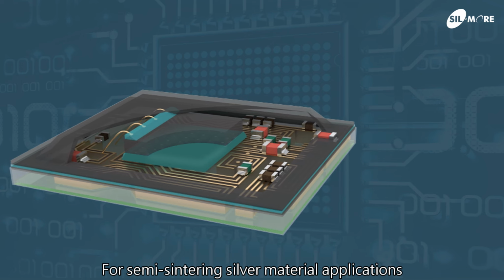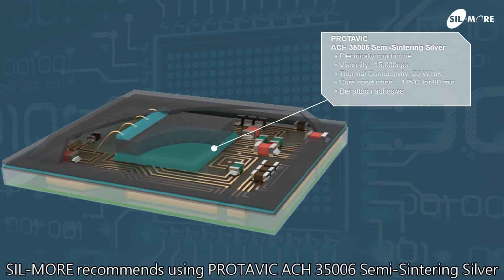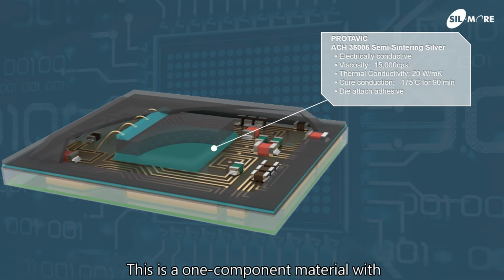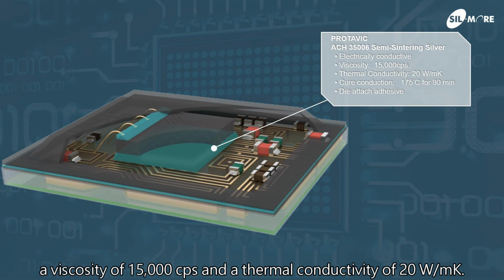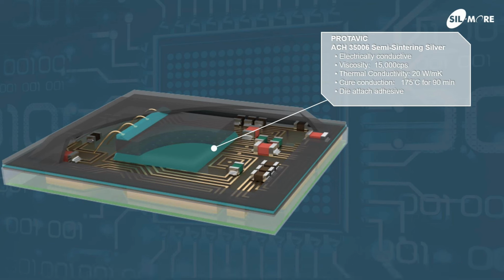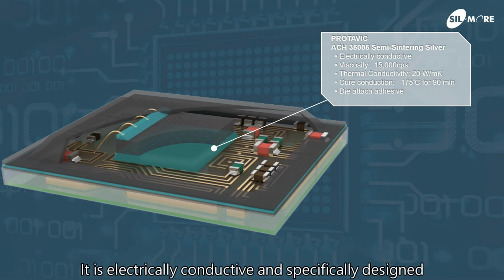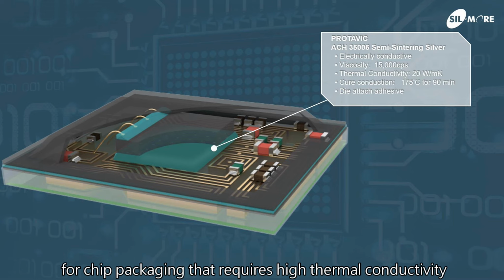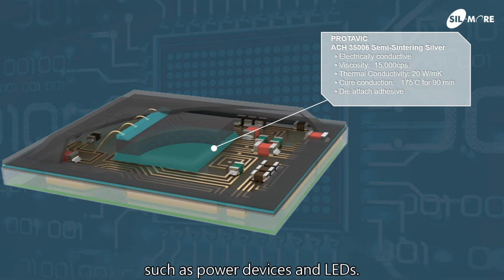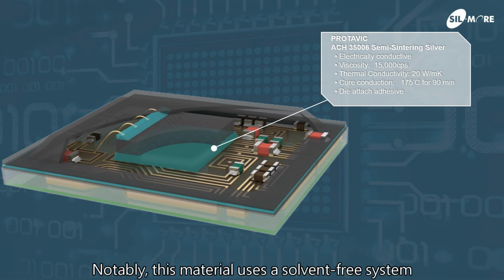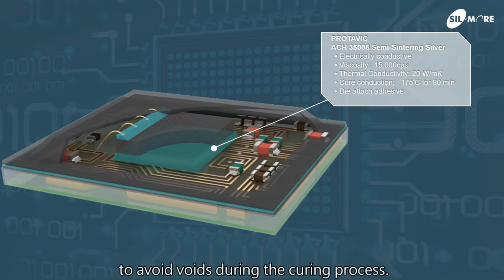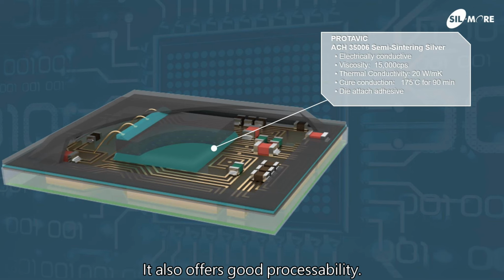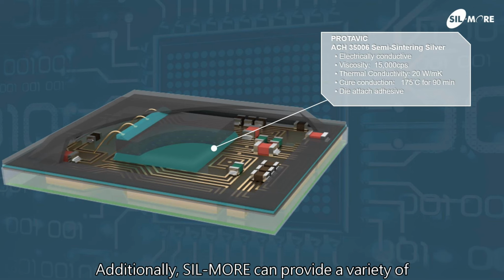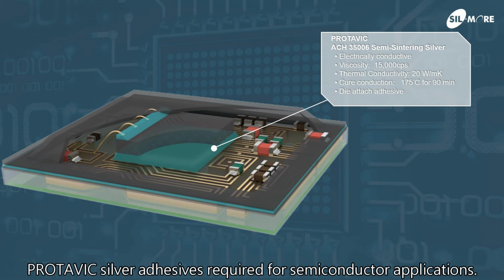For semi-sintering silver material applications, SIL-MORE recommends using PROTAVIC ACH35006 semi-sintering silver. This is a one-component material with a viscosity of 15,000 CPS and a thermal conductivity of 20 W/mK. It is electrically conductive and specifically designed for chip packaging that requires high thermal conductivity and good electrical conductivity, such as power devices and LEDs. Notably, this material uses a solvent-free system to avoid voids during the curing process. It also offers good processability. Additionally, SIL-MORE can provide a variety of PROTAVIC silver adhesives required for semiconductor applications.